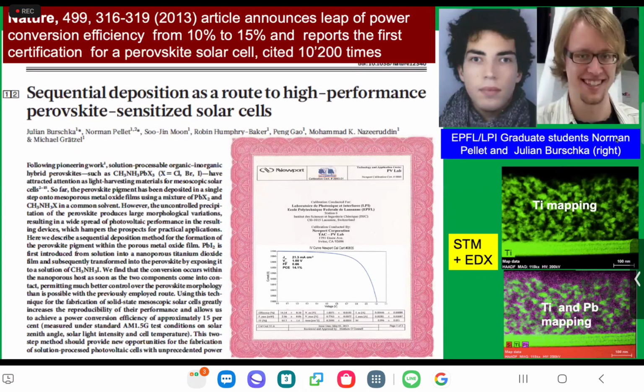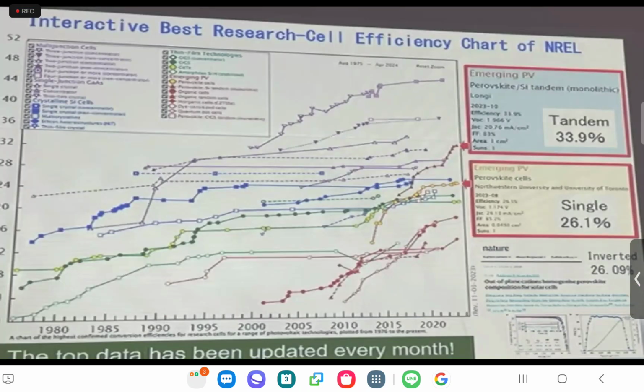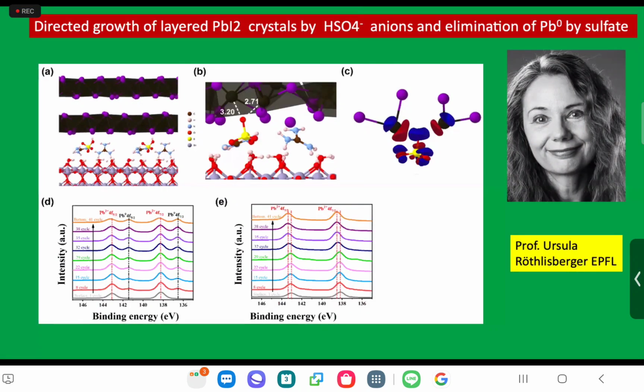Okay. And also one other thing that is important is in this paper, we showed that when we impregnated the TiO2 film with the perovskite, it filled the pore space and formed a capping layer. That gave us the higher currents, okay? And that moved the efficiency from 10 to 15%. That's a 50% improvement within a couple of years. And so the reason why this direction happens is twofold.